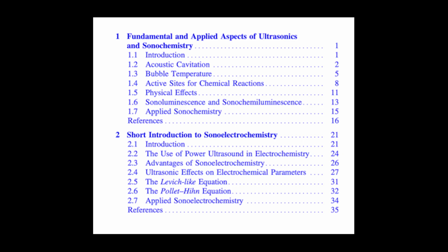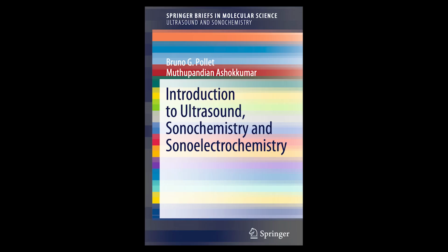So it translates current density into how fast the liquid would need to be flowing past the electrode to give that same current density. Exactly. It essentially says the mass transport conditions created by my specific ultrasound setup are equivalent to having the electrolyte flow past the electrode at, say, 0.5 meters per second.